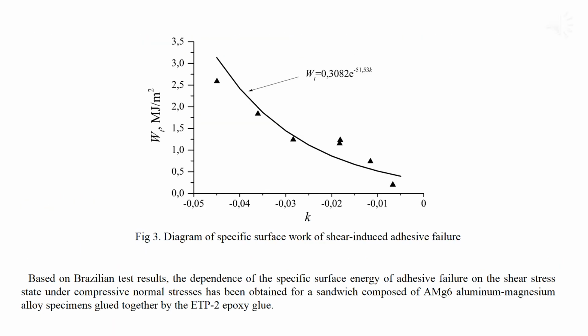Based on Brazilian test results, the dependence of the specific surface energy of adhesive failure on the shear stress state under compressive normal stresses has been obtained for a sandwich composed of aluminum-magnesium alloy specimens glued together by ETP-2 epoxy glue.